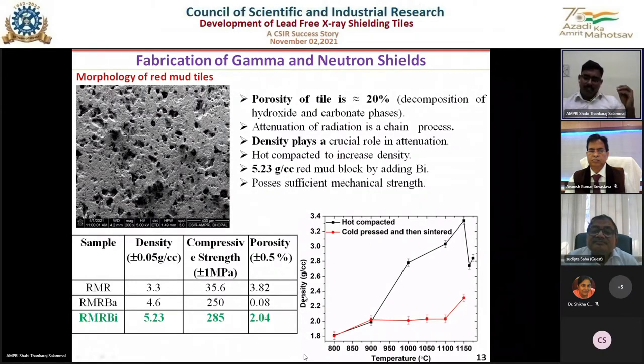For example, here you can see for the pure red mud, through the normal ceramic route, we made cold press and then fired. Up to 1200, the density is a maximum of 2.2. But when we use hot press, we get up to 3.4 gram per cc. And by adding some high-Z metal, we reach up to 5.23 gram per cc. We also have very good compressive strength. For pure red mud, we have close to 35 MPa, and for the bismuth sample it is 285 MPa, which is more than sufficient for building applications.